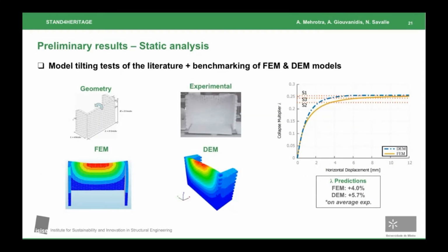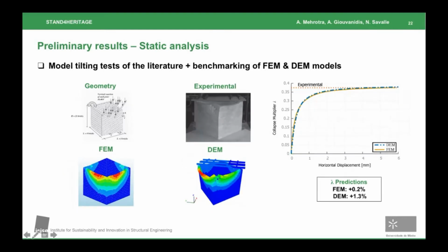Numerical modeling in both FEM and DEM is also used to model tilting tests from the literature, with the objective of also benchmarking the different modeling procedures. For a simple U-shaped wall, both procedures were found to compare reasonably well, correctly predicting both the experimentally observed failure mode as well as the collapse load multiplier to within 6% accuracy. The two modeling procedures were also found to very accurately reproduce the quasi-static response of more complex structural configurations, both in terms of geometry as well as boundary conditions.